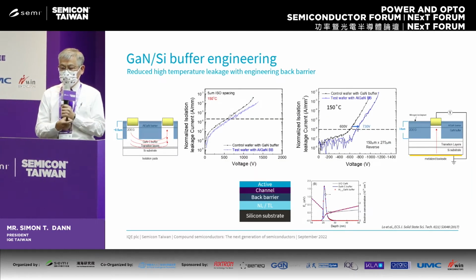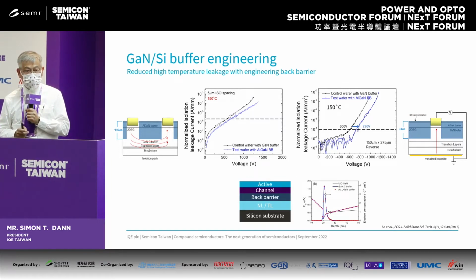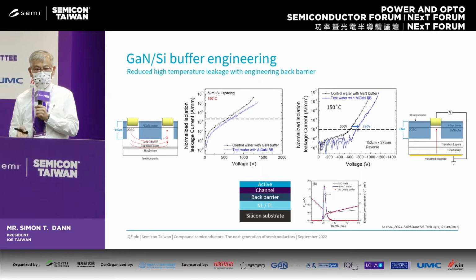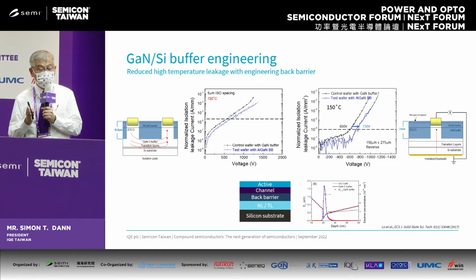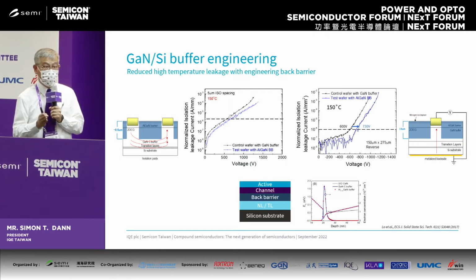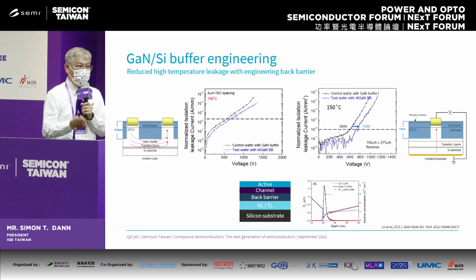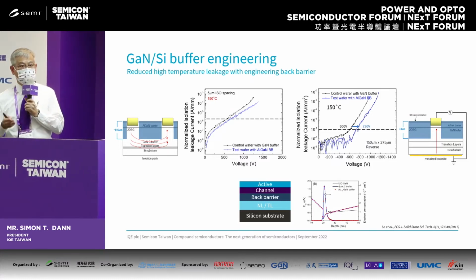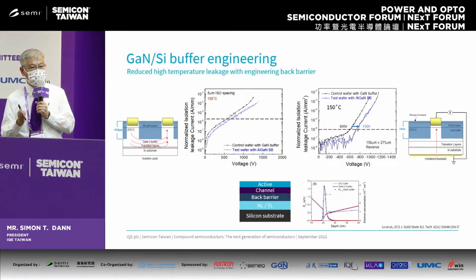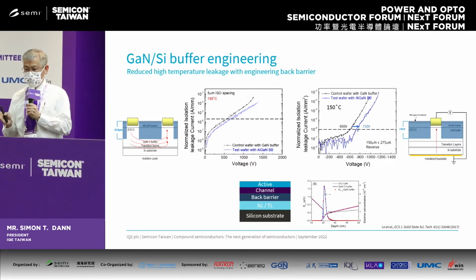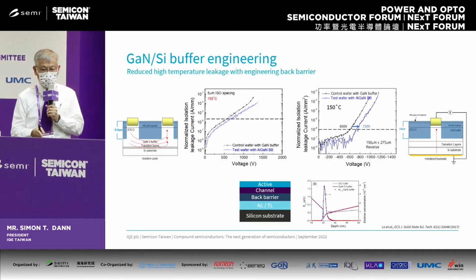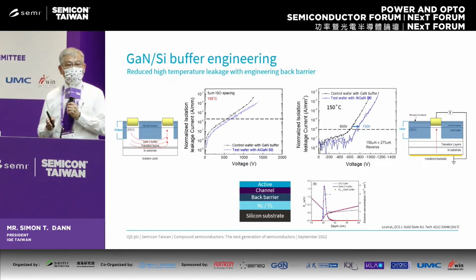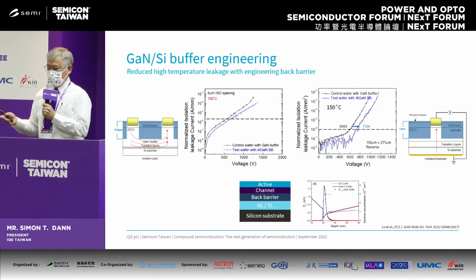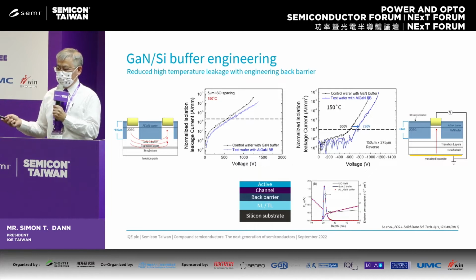Okay, then gallium nitride on silicon. There's another technology provider, IQE, can producing the back barrier to reduce the leakage current at high temperature. So for device operate at a higher temperature, you need very high heat resistance and also the low leakage. So IQE have technology of the back barrier to help the customer to reduce the leakage, actually increase the breakdown voltage.